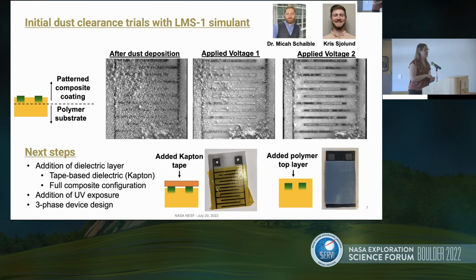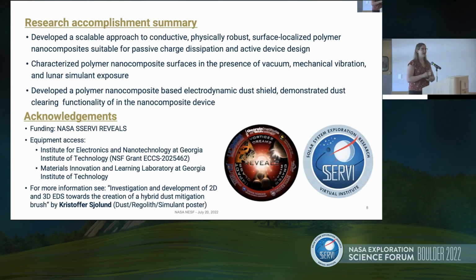We're also looking at adding UV exposure to assist with dust clearance and a three-phase design, which is a little bit closer to the state of the art of what works in rigid applications. So in summary, we've developed a robust, scalable approach to making conductive, physically robust, surface-localized nanocomposite structures. We've characterized those nanocomposite structures fairly thoroughly, beyond even what we've shown here, in the presence of vacuum, mechanical vibration, and dust exposure. And then we've developed a polymer nanocomposite-based device and shown that it is effective in clearing dust.